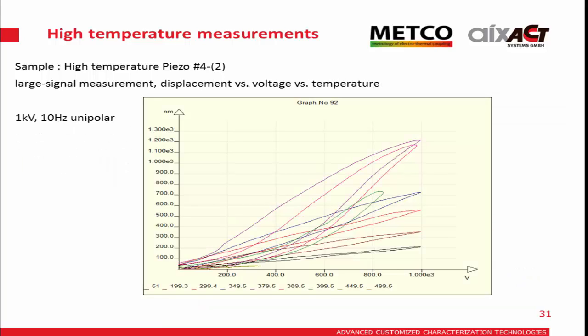And this is the individual displacement graphs. So you can see at lower temperatures the displacement starts to grow with temperature, and at high temperatures you can see the shape is changing, so you have something going on in the material. And for even higher temperatures, for example the green loop, it's going down again, but this is also limited because the current is not high enough.